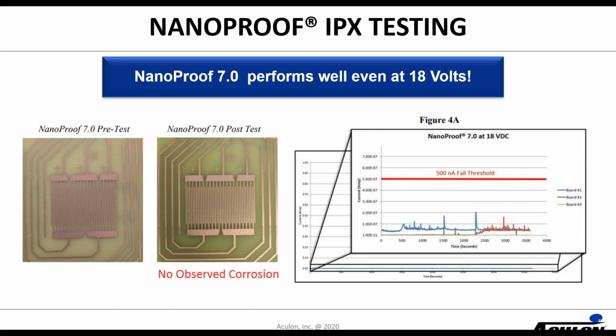They are not leaking current, and you can see that post-test, the test comb is nice and clean copper. If that was failed, it would be totally oxidized and green and bubbling. So it's a really good pass or fail test of these coatings.